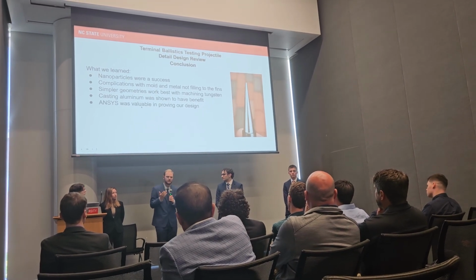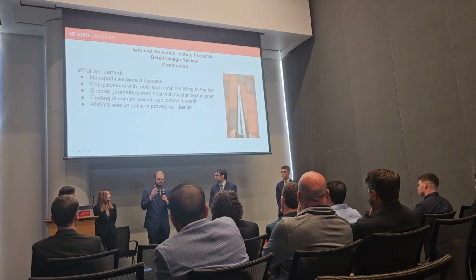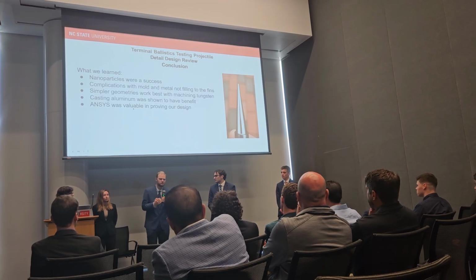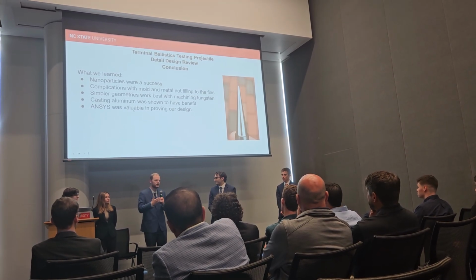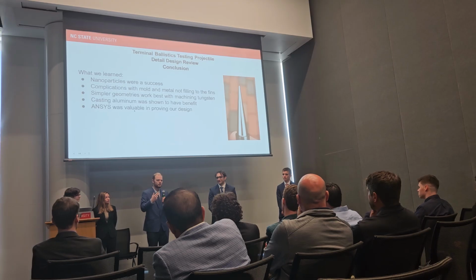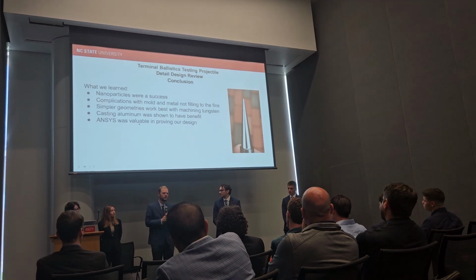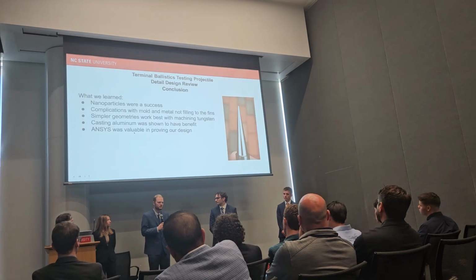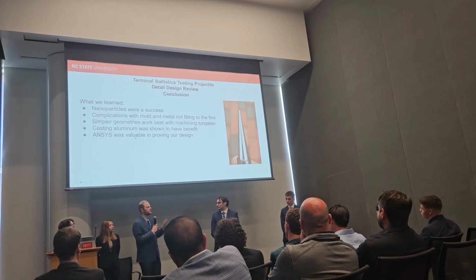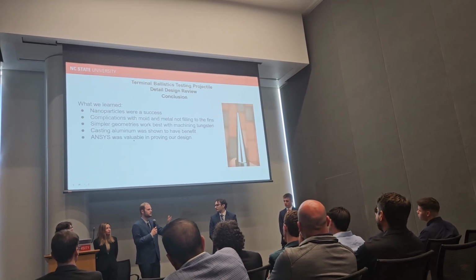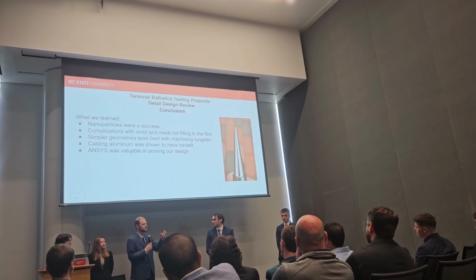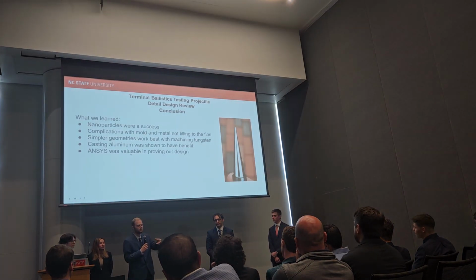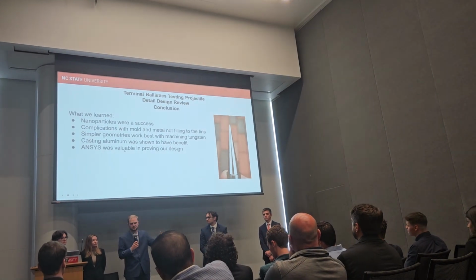With how we had it, our furnace was relatively small, so there's no way we could pour in it, and we were only able to pump argon through it and not have it completely vacuum sealed. Their furnace was at UC Berkeley and they had a lot more funding for this, but their furnace was the vacuum itself and they were just able to put the mold in there, pour the material, and then let it sit.